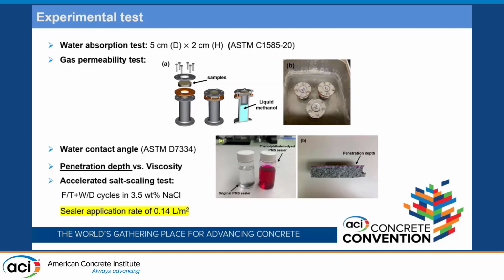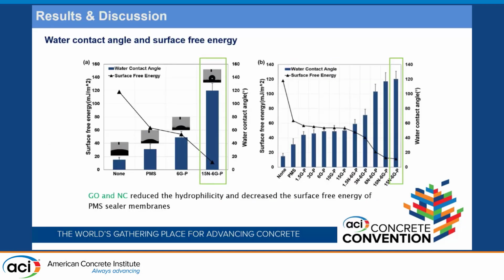So based on the instruction from many commercial sealers, in this study, the application rate of our sealer is fixed at 0.14 liter per square meter. Here is the water contact angle result. And the surface free energy can be calculated based on the water contact angles. So both these two parameters can be used to